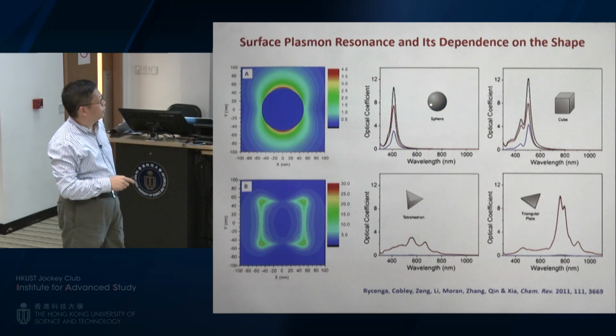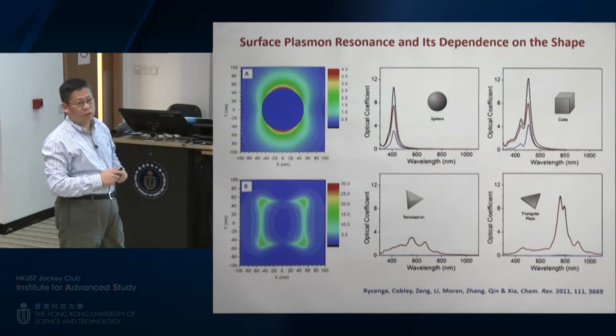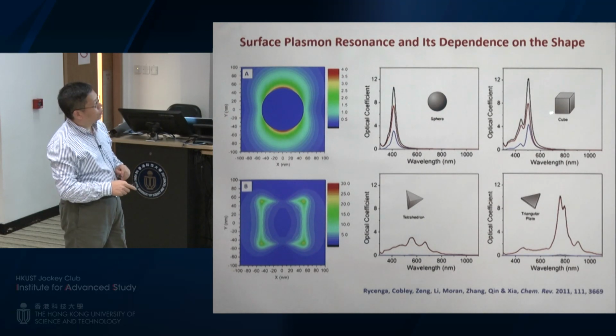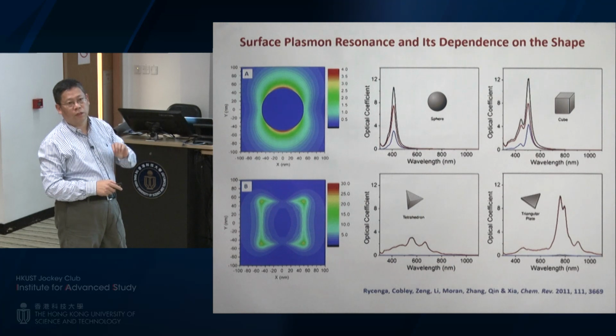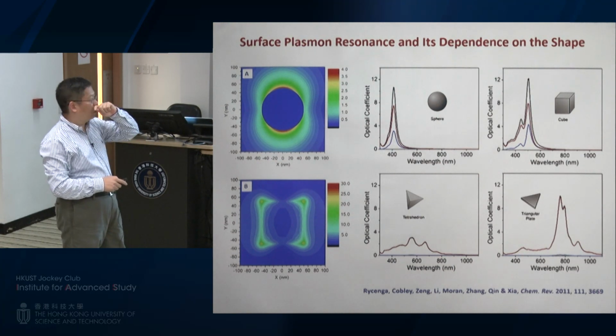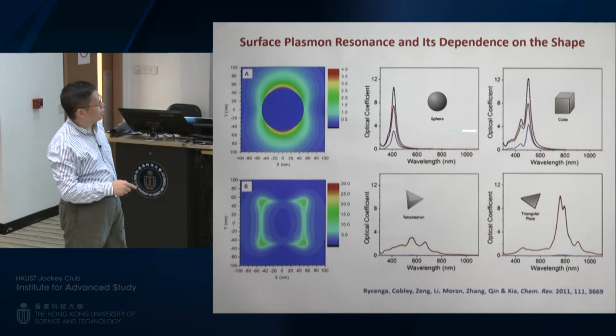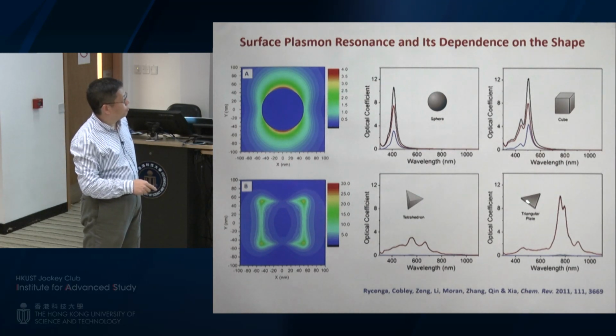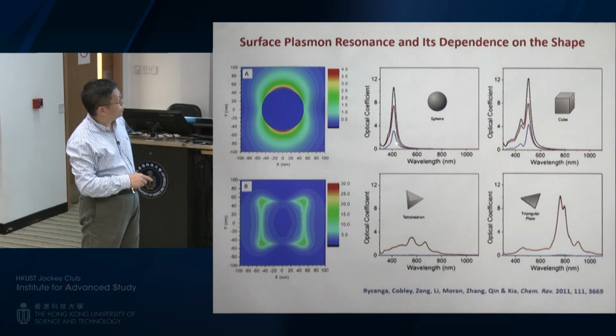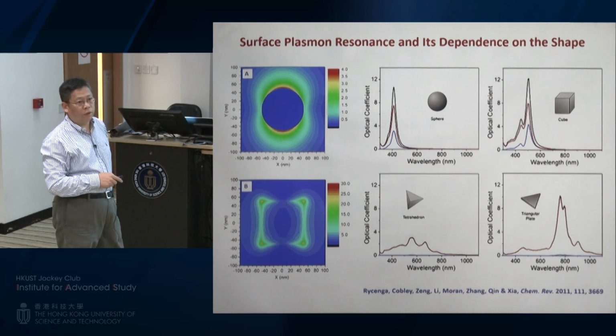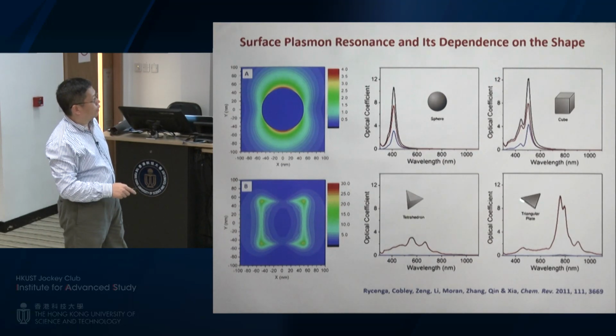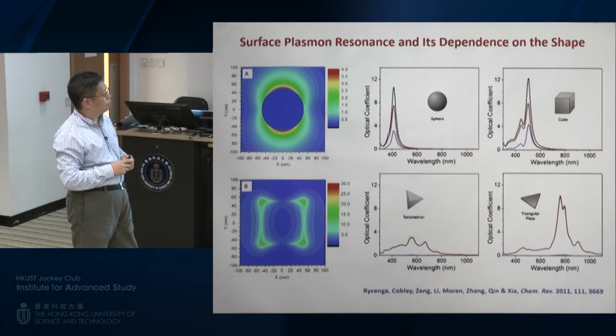Typically for spheres of this small size, you only observe one resonant peak. For silver, it's about 400 nanometers. However, if you switch to particles with lower symmetry, like a cube, you observe multiple peaks. Because the symmetry is reduced, there are a number of different ways to polarize the electrons, so the number of resonant modes is different. Also, if you switch to silver plates, you can see a significant shift of the resonance peak. In this case, it's almost 700 to 800 nanometers, while the lateral dimension is about the same, about 40 nanometers. It's really the morphology or shape that has changed.